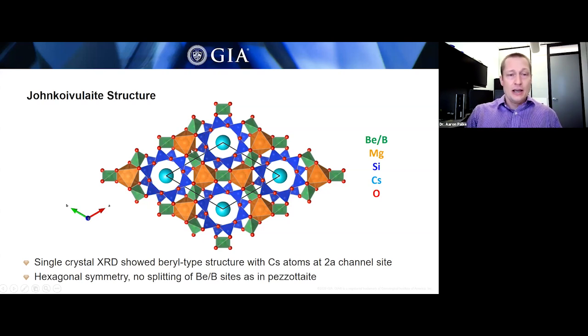In this case, the defining characteristic of the beryl group minerals is these rings of silica tetrahedra. These are 6-membered rings of silica tetrahedra. They have the formula Si6O18 because there are 6 silicons forming these rings with 18 oxygens forming the tetrahedra. And they're stacked along the C-axis. You can see 12 tetrahedra here. That's because they're stacked and kind of askew as they're being stacked down the C-axis.